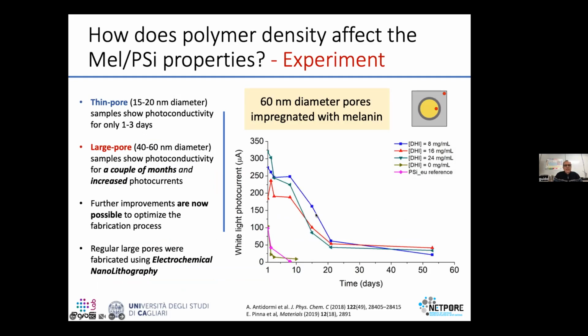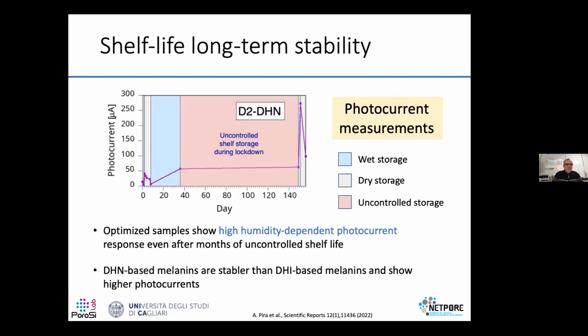And in particular, you can work on the stability of the system with respect to initial condition, the polymerization process, etc. This is just an example of what happens. This is a sample that has been left on the shelf without any control for some months during the lockdown during COVID, and you can see that even without any kind of control, at the end of the period, the sample is still extremely sensitive to the water content, and you still have the high peak due to the increase of the photoconductivity at high water level.